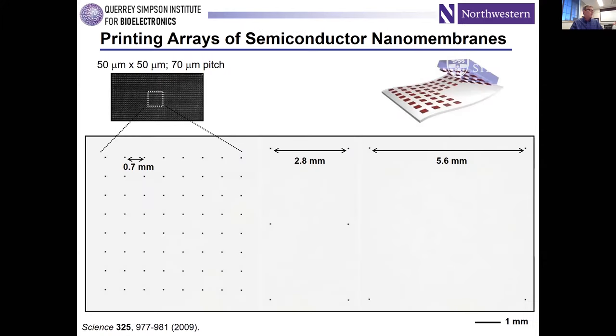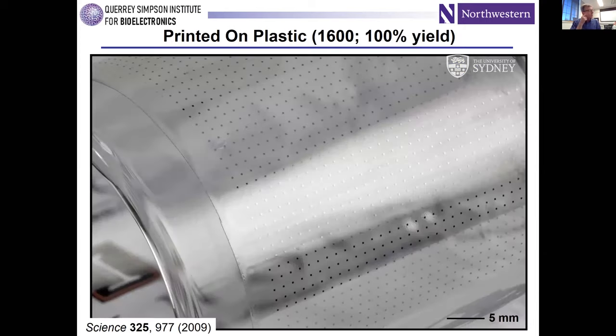So this is what it looks like. You have a high density of these semiconductor nano elements in a sequence of printing steps. You can now spread them out at any areal coverage on any kind of substrate because you're doing this at room temperature. So you can get a very high temperature material like monocrystalline silicon onto a low temperature substrate like PET or silicone rubber. And that's kind of how it works. And it works really well.